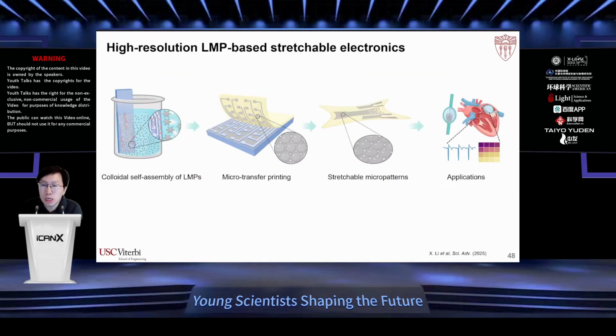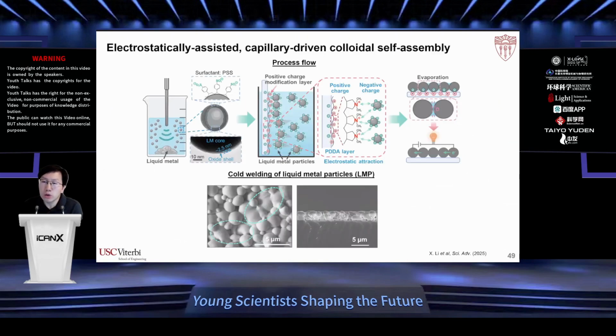So what we developed is a method to pattern and join individual liquid metal particles into micro scale thin films for stretchable conductors. The basic process is that we combine a colloidal assembly process so that we can closely pack and join individual liquid metal particles onto a substrate, which is stamped. We then transfer print the closely packed liquid metal particles from the stamp to our target substrate, which can be flexible, stretchable, such as silicone. The colloidal assembly process is a bit unique here, because what we want to achieve is a single layer of liquid metal particles that are closely packed and interconnected.